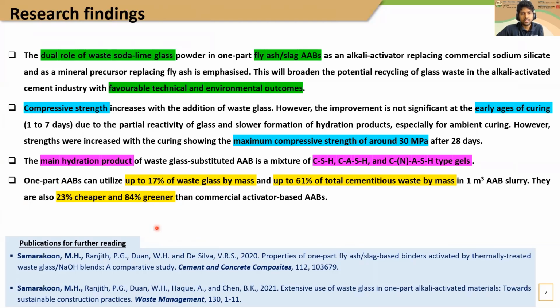Finally, one-part alkali-activated binders can utilize up to 17% of waste glass by mass and up to 61% of total cementitious waste by mass in 1 cubic meter of alkali-activated binder slurry. They are also 23% cheaper and 84% greener, that is emission effective, than commercial activator-based alkali-activated binders. If you are interested, you may refer to this publication for detailed results and discussions.